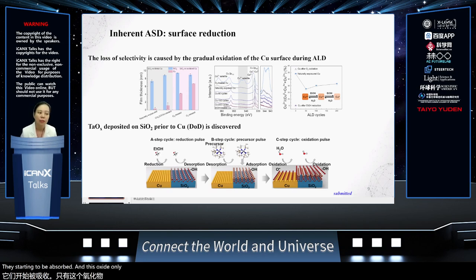Then when you run the second run, the byproduct, the co-reactant, either hydrogen, the water, or the oxygen, tends to oxidize the copper surface again. So you have to reduce the copper again. By doing so, we actually invented this kind of ABC type of ALD process.